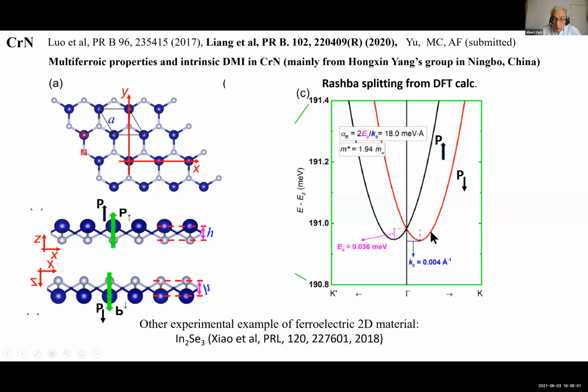For example, typical Rashba dispersion curves, depending on the polarization, P down or P up, show this shift of the parabola depending on the direction of the ferroelectric polarization. So these systems are certainly metallic, and what can certainly be exploited is the Rashba effect and the possibility of changing the polarization, the sign of the Rashba constant,